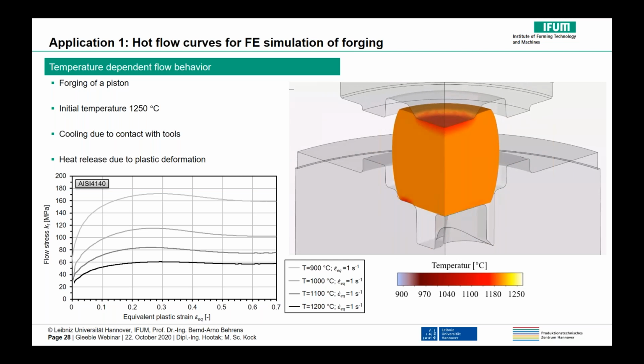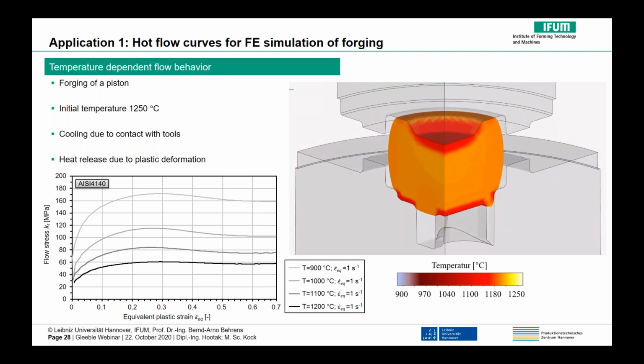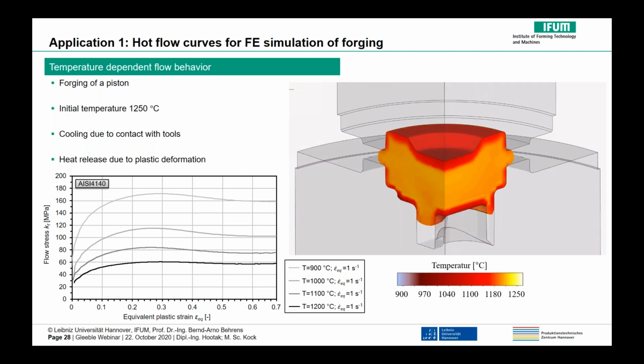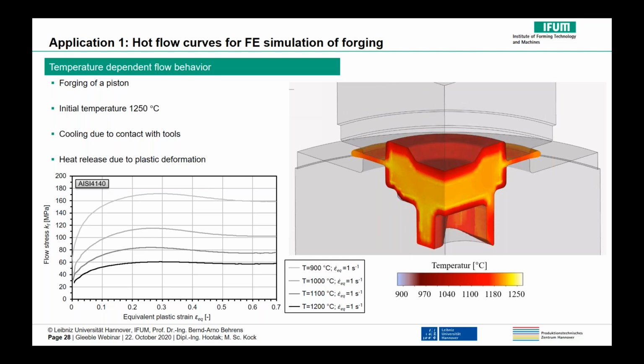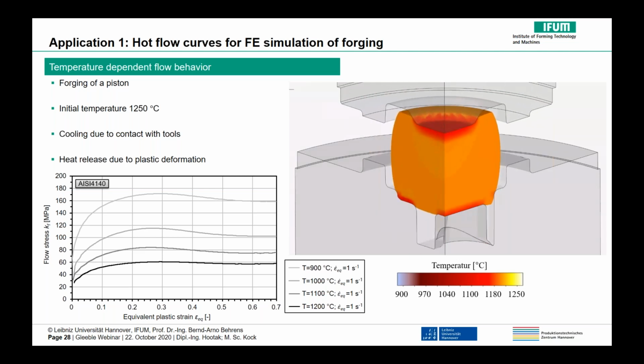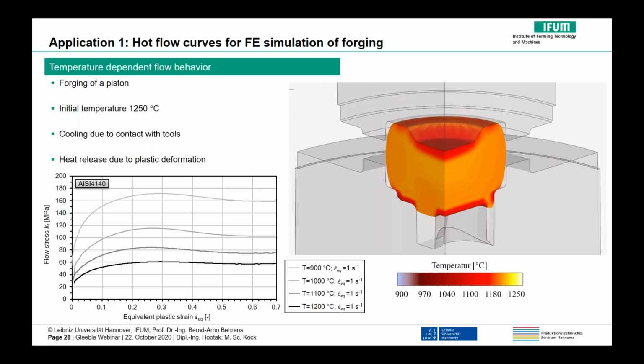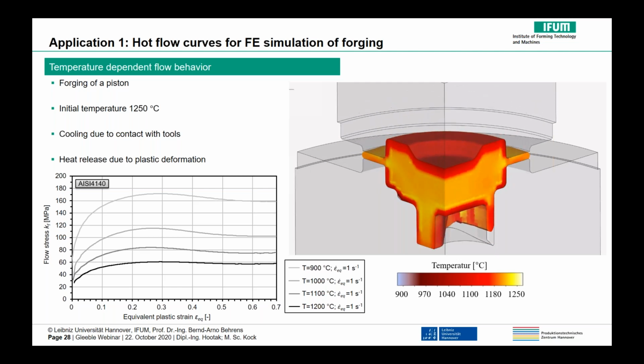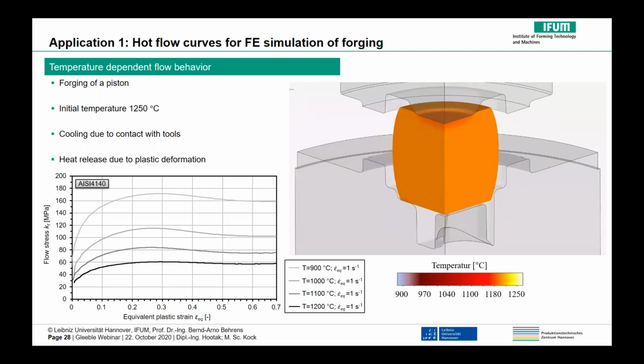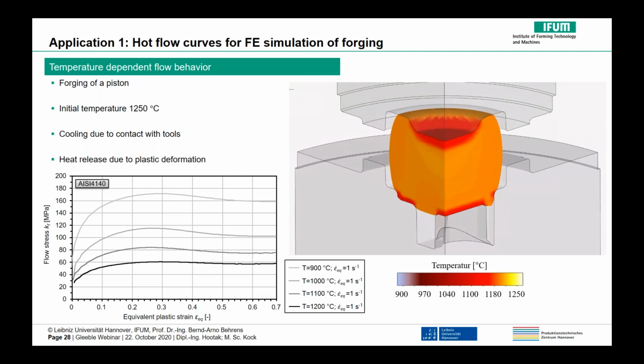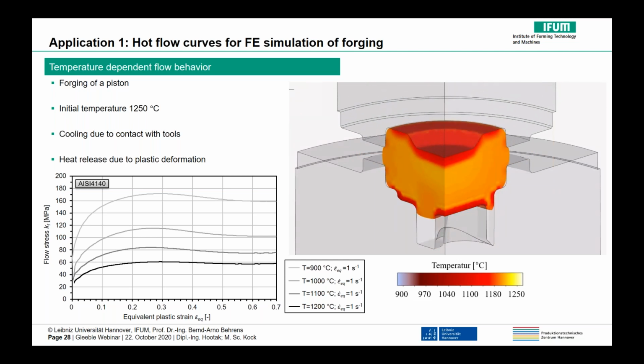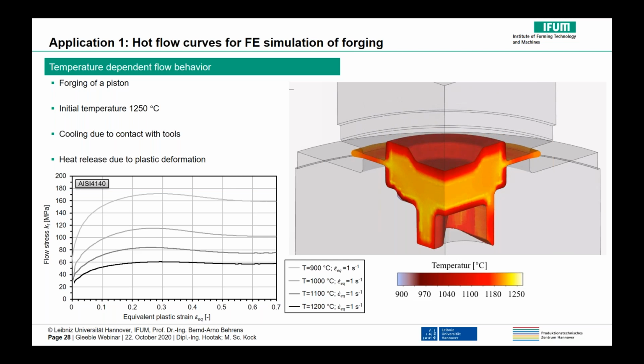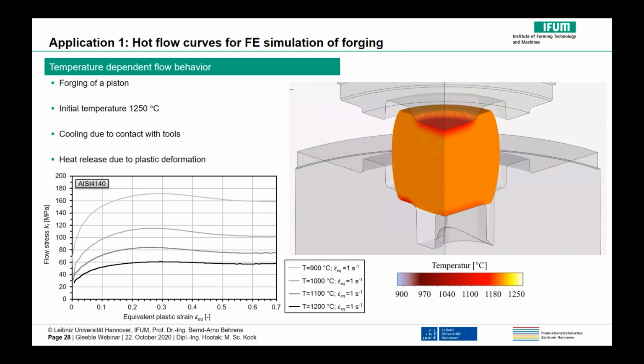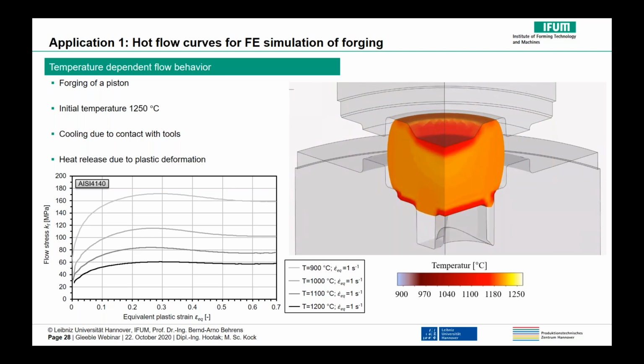Furthermore, the simulation also takes into account the heat release due to plastic deformation, which explains the permanently high temperatures inside the material. As can be seen by the flow curve in the diagrams on the left, this observed temperature gradient means that locally different flow stresses and consequently different forming conditions prevail. It demonstrates how important the temperature-dependent material characterization is.